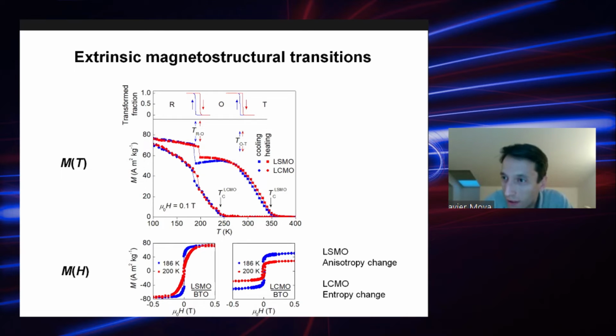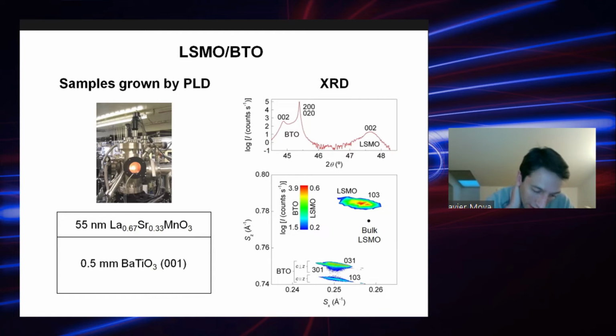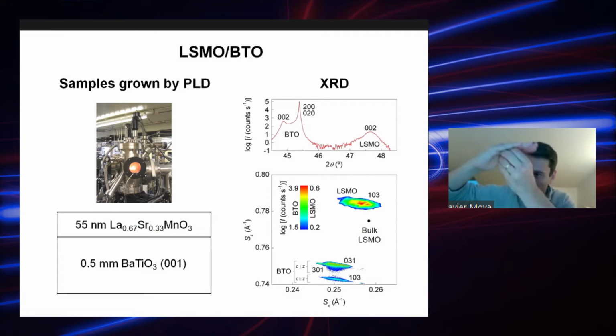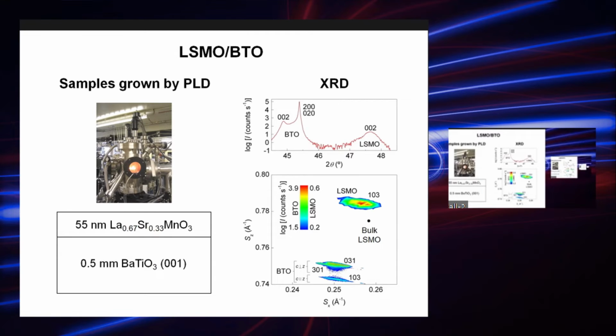Then what we've done after is focus on the other sample, the LSMO, in order to study these changes in anisotropy. Just to give you a bit more detail, these films in particular are 55 nanometers thick, and they are grown on 0.5 millimeter barium titanate substrates by pulsed laser deposition. This is a picture of the chamber. You have your material target, and you hit it with a very high fluence laser, so you can vaporize the target material and deposit it in a very controlled manner on the substrate. So you can make these epitaxial films that have very good strain coupling.